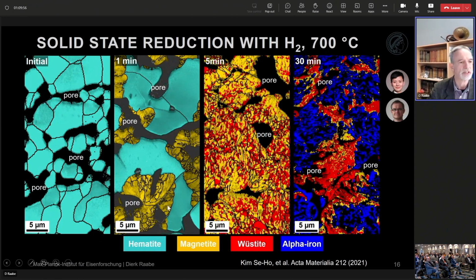I mean, there are relevant details. But what is really interesting when you look into the transformation from the spinel into the cubic wüstite, then you see a very interesting type of gradual decomposition where the iron seems to be reshuffling on the remaining cubic lattice. And it's also, by the way, in the EBSD not so easy to measure because both are cubic structures. It's quite complicated actually to measure. And this is something I'm currently very interested in, the nature of this funny type of phase transformation.